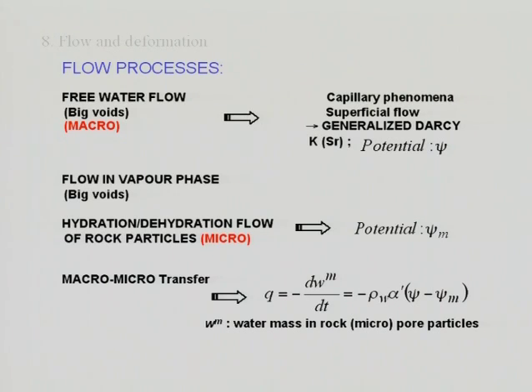We may have free water flow going around the big particles, the macro. Probably capillary phenomena have something to say here, superficial flow. Well, we may try to generalize Darcy flow by simply specifying that the permeability is a function of the degree of saturation, as we do in unsaturated soils. But here we have this total potential, the macro potential, controlling the flow of water. We have also flow in the vapor phase, which maybe is very important and more relevant in many cases. We have to include that. And then we move into the particles, the micro, and then we define here a different potential.